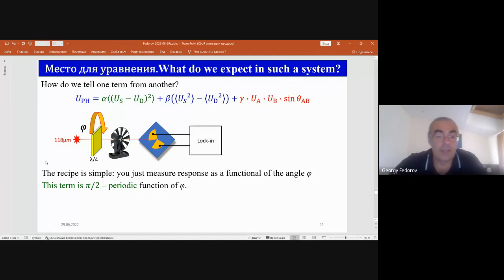And it's pretty easy to show that the first term here should be a pi over 2 periodic function of phi, which is very straightforward and clear because you just come to the same polarization every 90 degrees. You have the same periodicity for the second term. Once again, you just come to a linear polarization state every 90 degrees. But for this term, every 90 degrees, you go to circularly polarized light at the outcome of the lambda over 4 plate, but you change the direction of the electric vector rotation. So you go from sigma plus to sigma minus if you rotate the plate by 90 degrees. And this term is asymmetric. It has the sign of this phase difference. So in general, this term will give you a pi periodic contribution to the response of the device.